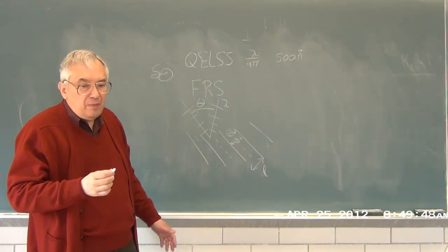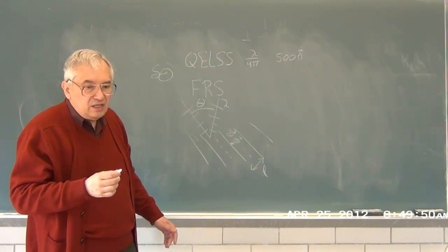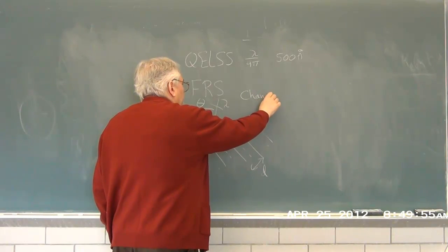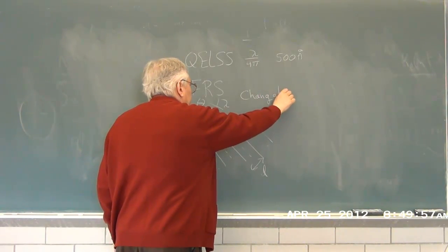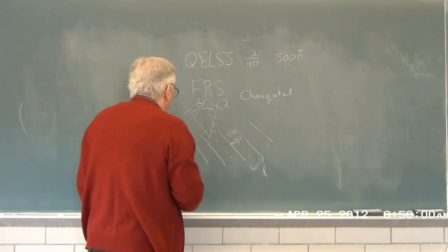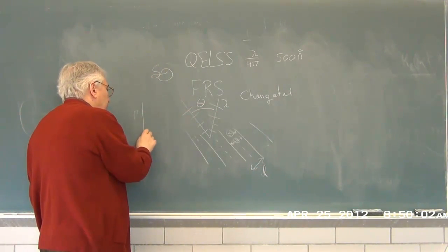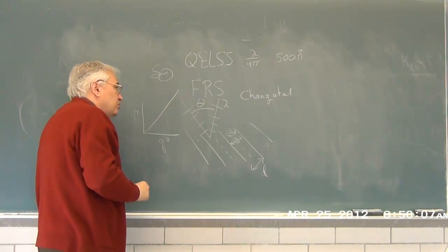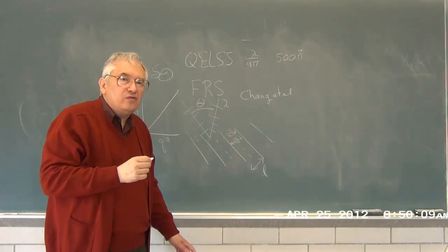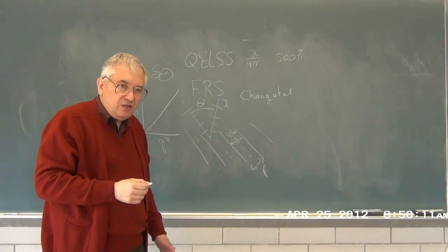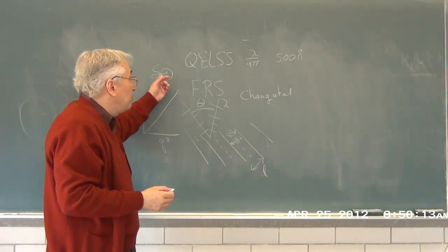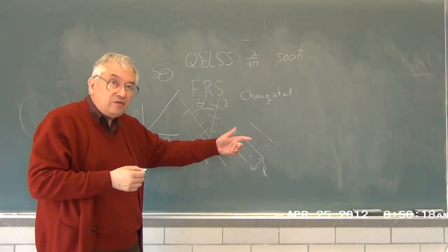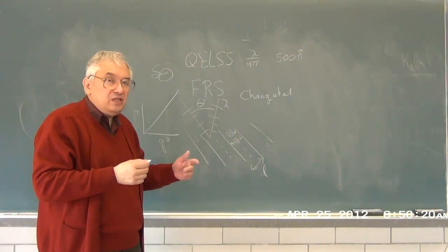And there are several people who have done this, for example, Chang et al., find that if you plot gamma, the relaxation rate, versus q square, you get out this nice straight line which covers orders of magnitude in particle distance. And therefore, diffusion over fairly small distances and diffusion over very large distances proceeds at about the same rate.